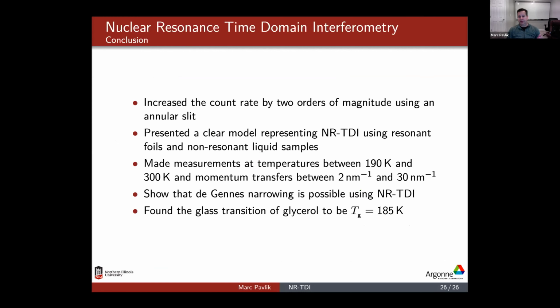So what we are able to do is increase the counting rate by 2 orders of magnitude. We hopefully presented a clear model to represent nuclear resonance time domain interferometry using resonant foils and non-resonant samples. We were able to do some de Gennes narrowing, and for glycerol, we found the glass transition to be about 185 Kelvin, which is within the literature that we found out there.